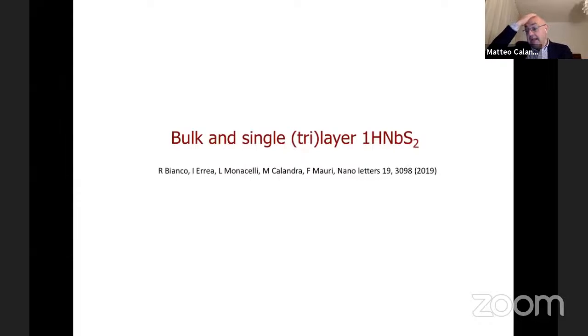So let me conclude with one last example, that is the bulk and single trilayer 1H niobium disulfide, and this is a very old problem that has puzzled me since 2012. At the time, anharmonic calculations were at their infancy, and essentially we were not able to calculate anharmonic corrections, and everything was based on harmonic calculations. Apparently, if you take most of the bulk metallic dichalcogenides at the time, it was fairly clear, everyone was thinking, including me, that harmonic calculations were giving stability at the right points, and there seemed to be no room for anharmonicity.